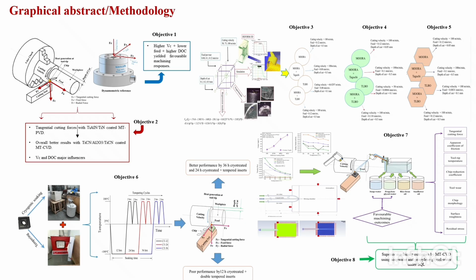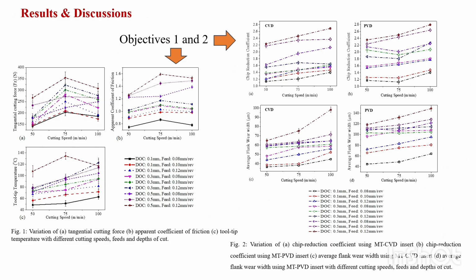So this is the graphical abstract and methodology. Result and discussion. This is the first objective. What we can see from the FZ plot: tangential cutting forces for a particular feed rate and depth of cut have increased with rising cutting speeds. Increase in cutting velocity has led to increased friction, thereby raising the cutting temperature and BUE, which in turn had caused an upsurge in the requirement of cutting forces.